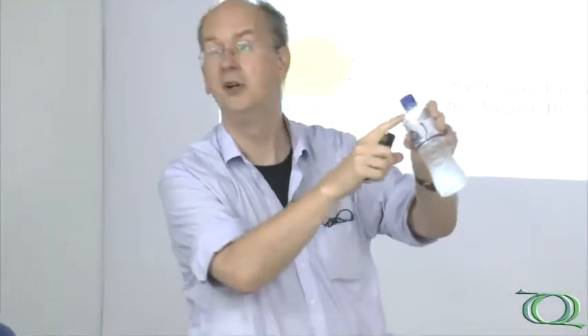And then the PIM materials are a newer development. They are polymers of intrinsic microporosity. They are polymers like this, but this polymer here is PET. It's very non-permeable, so gas will not go through this polymer. But the polymer with intrinsic microporosity looks the same, but it's completely permeable. So gases, small molecules, can very easily go through the polymer. And so we are interested in the electrochemistry and how ions can move.